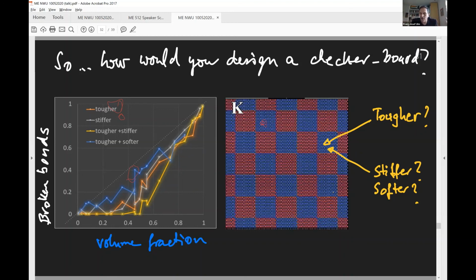So a little bit like the classical way how we deal with bounds in mechanics, the best economic solution to obtain the highest toughness is not by going tougher and stiffer. Actually, tougher and stiffer is this yellow curve, you see, which just reinforces the percolation threshold. It is actually the tougher and softer material. By the way, a problem which is well known from shale gas.